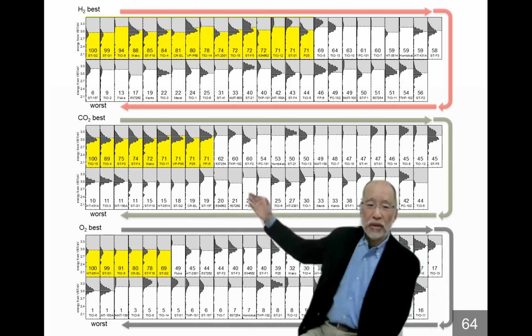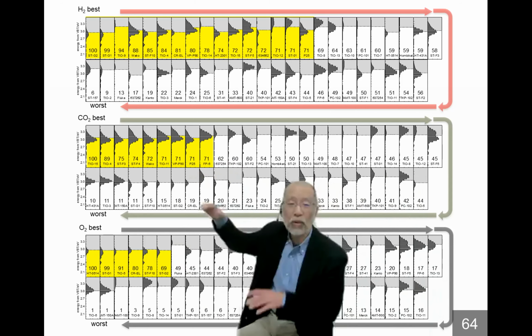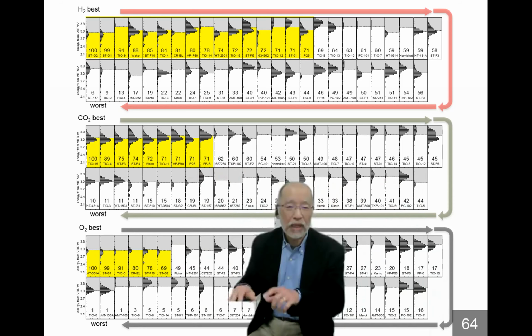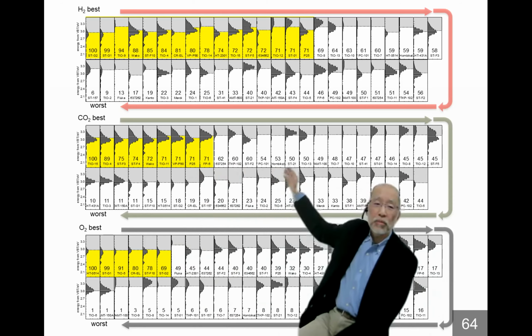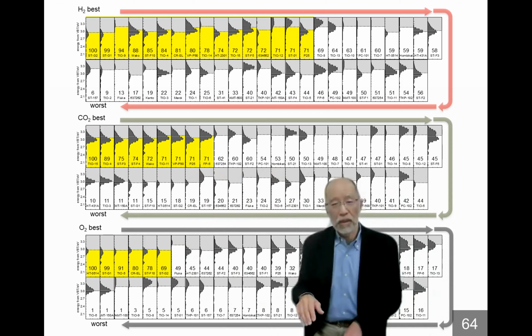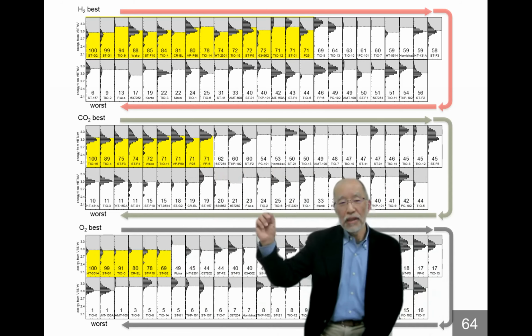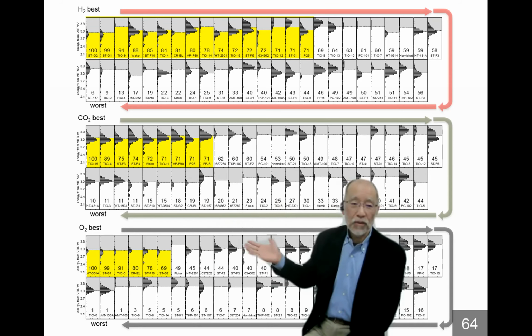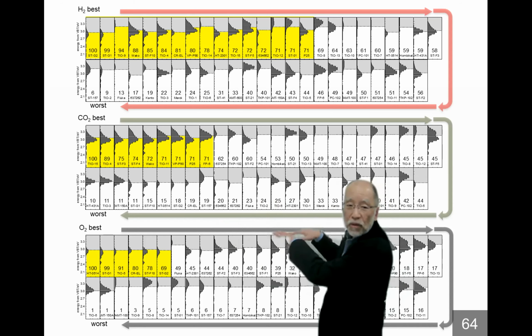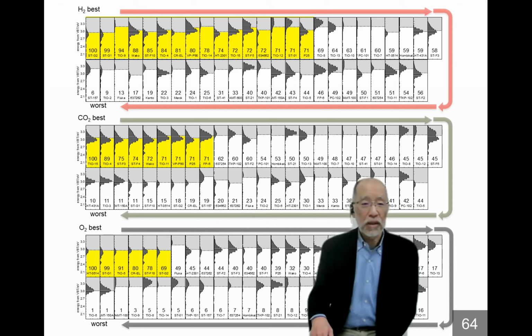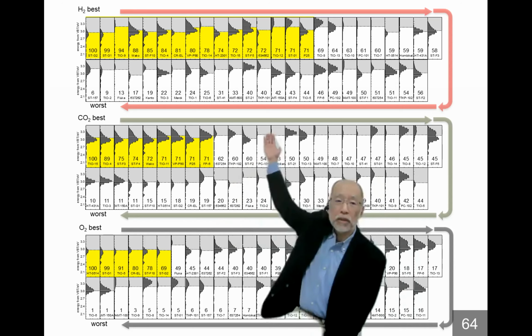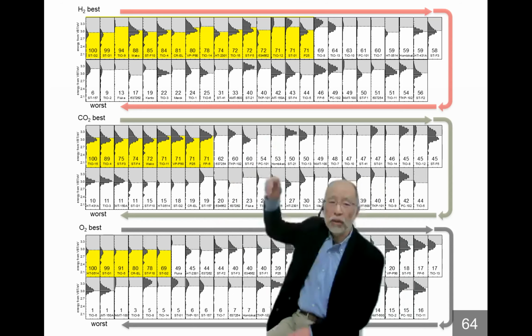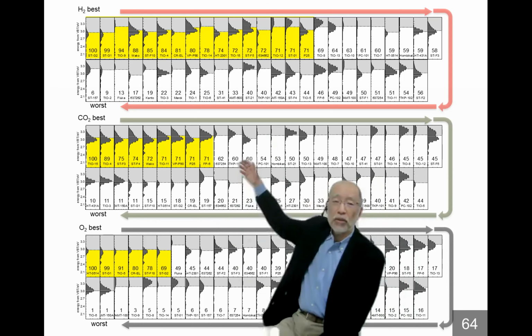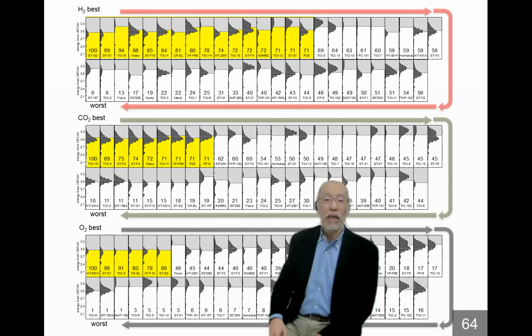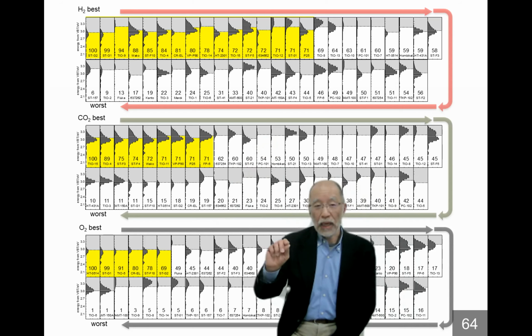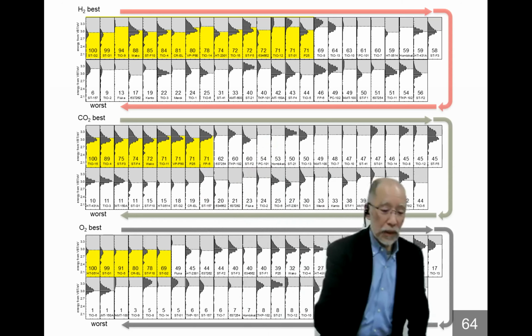So that is important. Those photocatalysts are well balanced in several structural parameters, but those middle or low activity samples are inactive for different reasons. Sometimes, for example, the specific surface area problem, or sometimes the defect problem, or another kind. So the reason for low activity differs. For the hydrogen case, in situ platinum deposition is included, so it is a two-step reaction and not completely well balanced. That means it is possible to expect a higher photocatalytic sample by controlling the reaction conditions.